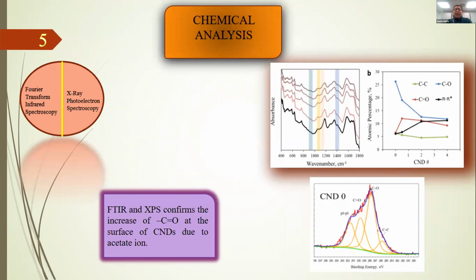To explain the anomalous behavior, we did chemical analysis. Chemical analysis is mainly done by 2 kinds of major experiments: one is FTIR, another one is XPS. In XPS, as you can see, there is a significant decrease in the C-O and C-C. However, there is a clear increase in the C=O and pi-pi star interaction on the surface of CND with the addition of acetic acid.